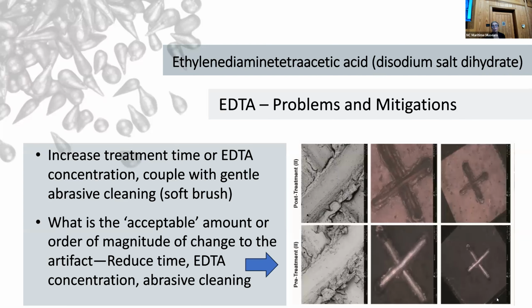In terms of damage, a lot of it comes down to what do we consider damage? What is significant? What is an acceptable threshold or magnitude of change we're willing to accept with these treatments to get what we want out of them? So you can see this is a comparison of the before treatment and after treatment of these details, where you can see that this treatment did affect a lot of the surface in some places. There's material that's missing, there's material that's been changed, there's material that's been eroded away.